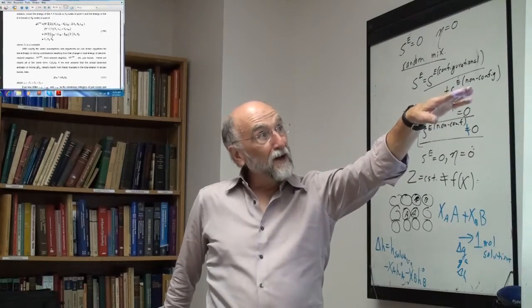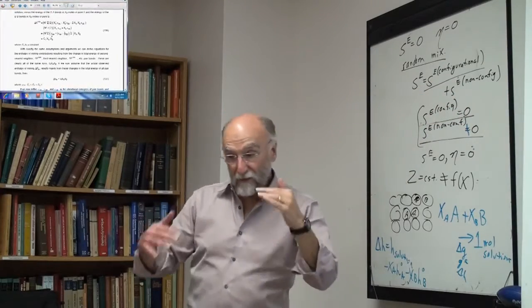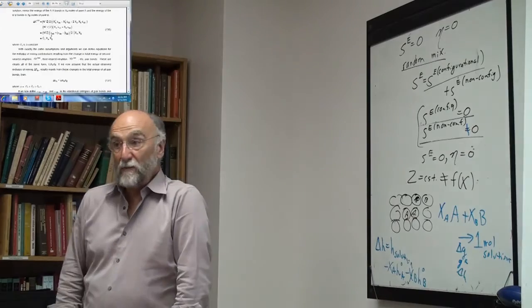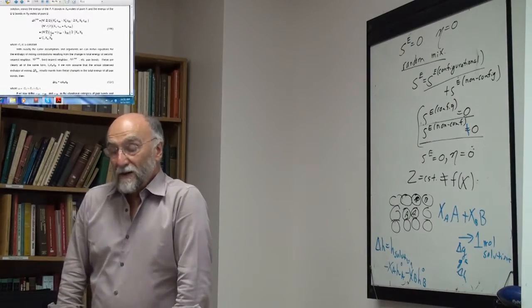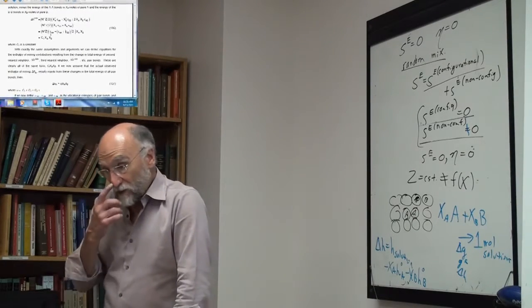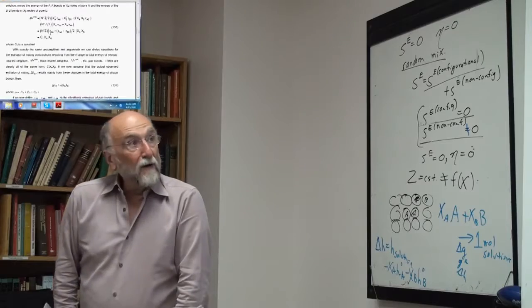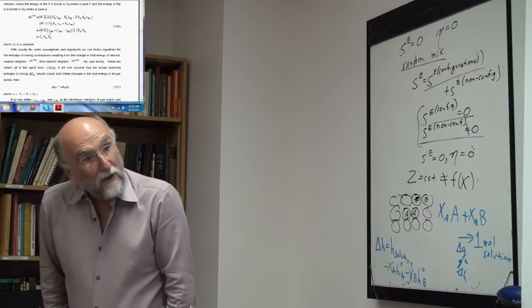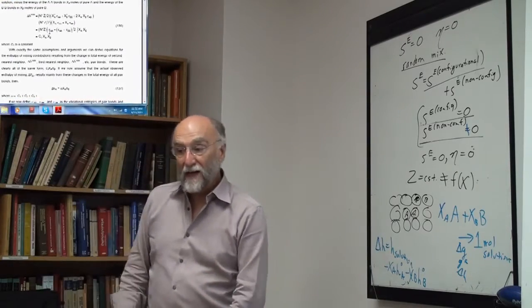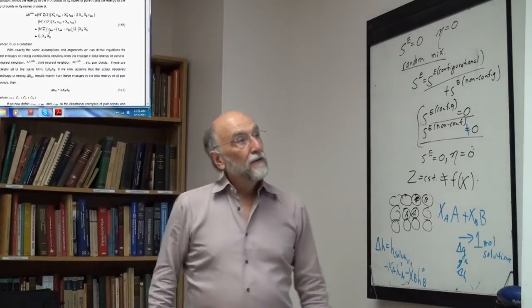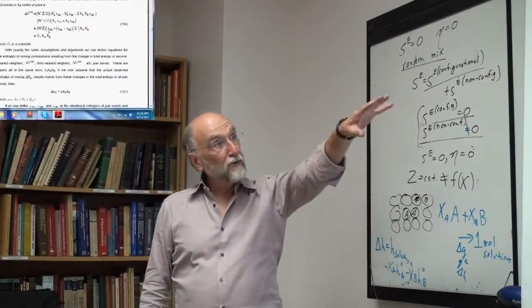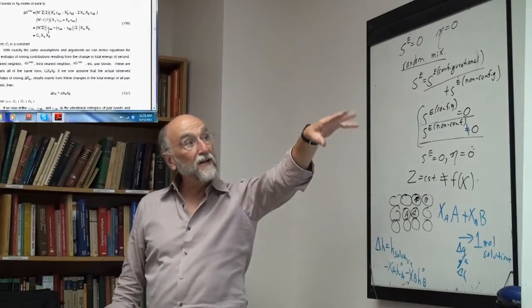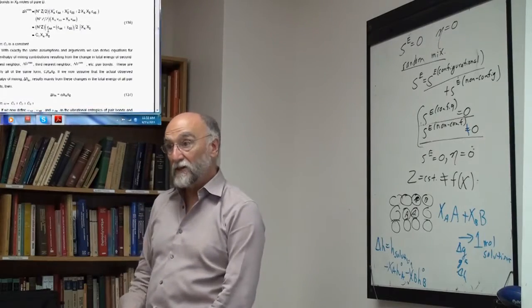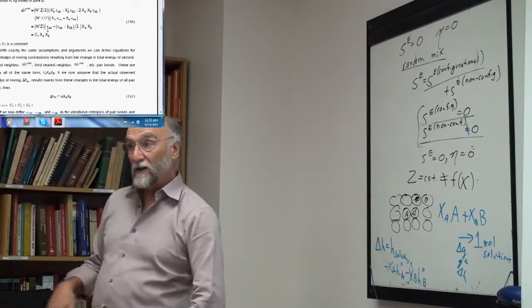SXS will be non-ideal, delta H will be non-ideal, and it'll find the balance that gives you the minimum G excess. Okay, and we'll do that in the quasi-chemical model. But I will tell you that in the quasi-chemical model, you can show that if the deviations from ideality are small, then it's still a reasonable assumption that the TSXS term is less important than the delta H term. I'll show that mathematically later on.